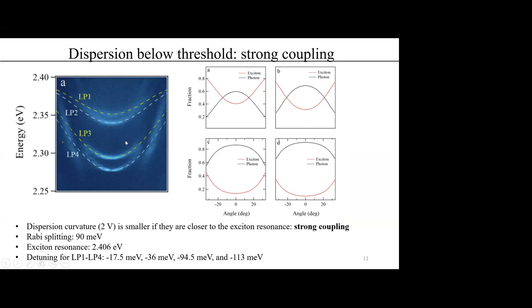We measure the dispersion of the macrocavity when the laser pumping density is below threshold. We observe several sets of modes, LP1 to LP4, which have different curvature due to different detuning with the exciton resonance. When the modes are closer to the excitons, the dispersion curvature is smaller. I think this is the signature of the strong coupling within a long cavity length macrocavity, which can sustain several cavity modes. Of course, the curvature of these polariton modes is much smaller than the cavity modes we discussed in the last slide. We fit this polariton dispersion by the coupled oscillator model, where we can get the Rabi splitting and the detuning for all these modes.